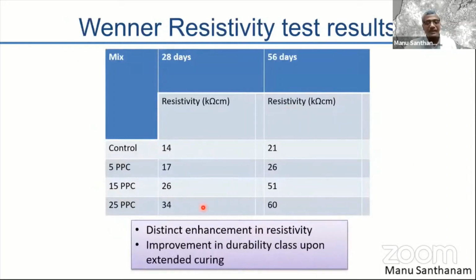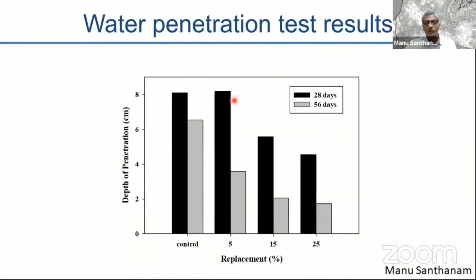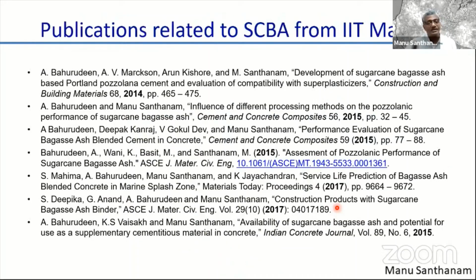Resistivity, again, you see an enhancement in resistivity. That means that you'll have a much better performance as far as corrosion is concerned. Water penetration is also significantly reduced when you replace cement with bagasse ash. So all this, of course, is indicative of the fact that you produce a material which is capable of reacting and also capable of functioning as a filler that overall reduces porosity and permeability and results in a much better microstructure of the concrete. So there are several publications we have on bagasse ash. Of course, you'll have a copy of this presentation, I presume, to see which paper you'd like to read and learn further about.